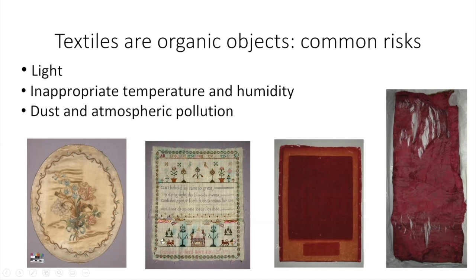In the UK, a humidity between 50 and 65% RH is usually recommended, but this can of course be subject to different interpretation in different areas of the world and even in different locations. So in a historic house, humidity is probably going to be controlled differently to within a museum, where it's easier to limit the humidity to within a strict range.